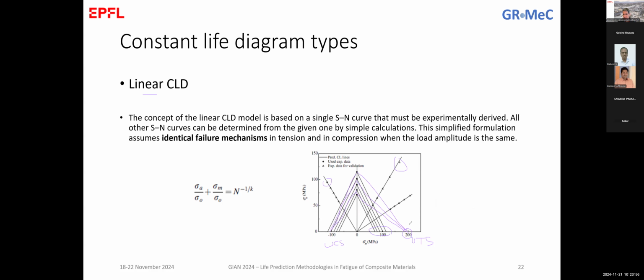The change between this and the Goodman diagram is that it assumes here that there is an effect of the time or the loading, even for the case where we have the horizontal axis here. You remember we talked about this yesterday. Here is the case R equal to 1, and this corresponds to a loading which is like that. We have sigma a and sigma m. We have a loading like this. We have a very high mean stress, but sigma a is 0. So here is 0. And if you plot this in the sigma m, you have a very high mean stress. So this is the case. Of course, there we can expect to have creep, and this is what is considered by this diagram by showing this change here in the horizontal axis. So this diagram is one that has been introduced. It's very simple, but it does not give good results, as you see here, and we'll see also later on when we compare.